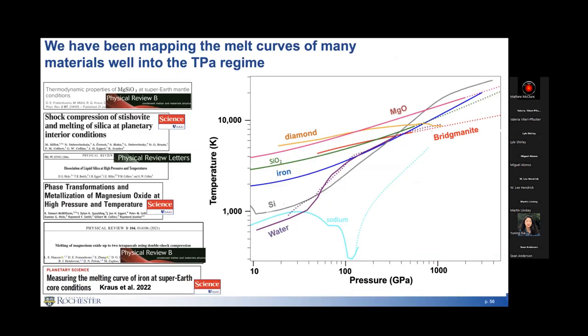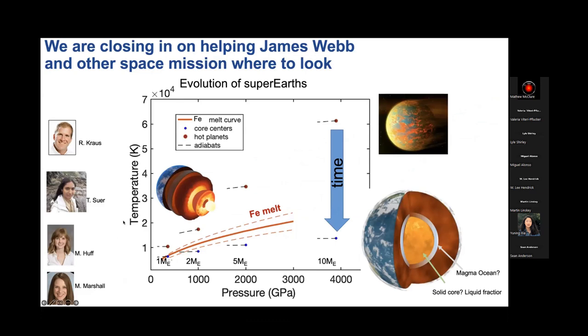We've been mapping out the melt curve for a number of materials. Usually I never show a plot without error bars, but this is the mean melting curves for a number of materials. One thing to note is that the melt curve of iron, while it starts out pretty low, which is good for Earth, ends up getting very steep compared to these different oxides. And what that means is that as you go to higher and higher pressures, so this is temperature versus pressure for iron, this is the melt curve that I just showed you, but over a more limited scale. If you build a terrestrial planet, it starts out very hot because it assembles.